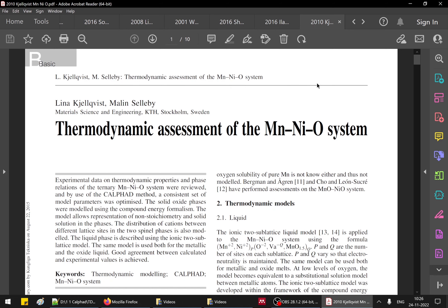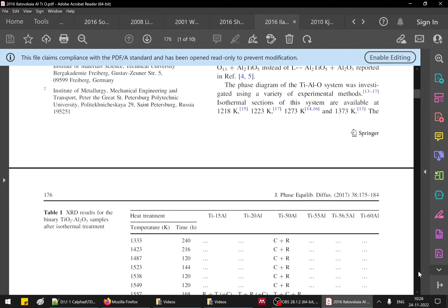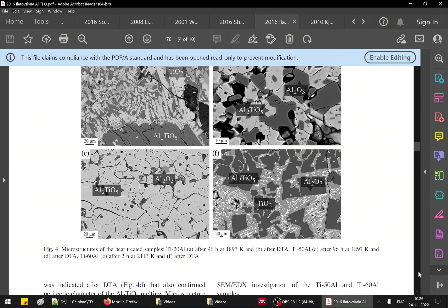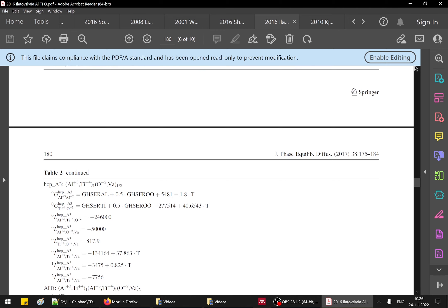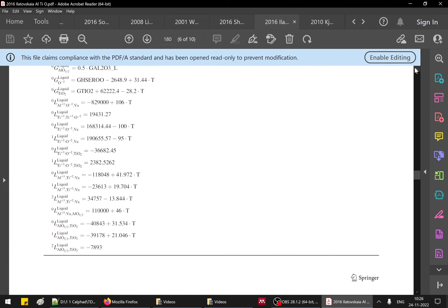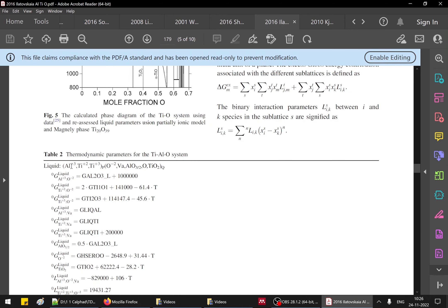With these names, the publications contain Gibbs energy descriptions. Scrolling down to one of the publications, you can see a table full of Gibbs energy descriptions — for example, the liquid phase containing aluminium, titanium, and oxygen. That is a sub-lattice model and the Gibbs energy descriptions are given as functions of temperature, with composition dependency also taken care of. This is the output of thermodynamic assessment, a curve-fitting procedure after critical evaluation of input thermodynamic data.